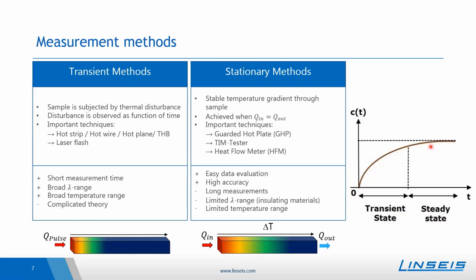So the transient methods already start measuring when there is a disturbance within the sample, and the most important techniques which belong to the transient methods are the hot strip, hot wire, hot plane methods, or also the THB, as well as the well-known laser flash method. The advantage of these methods is that they measure really fast, so they have a short measurement time just because they're already measuring when the thermal disturbance is brought in. They can measure a very broad thermal conductivity range as well as a broad temperature range.